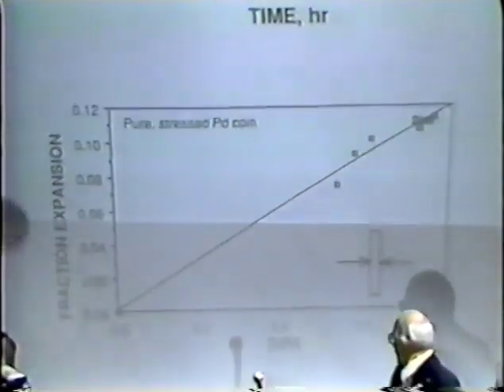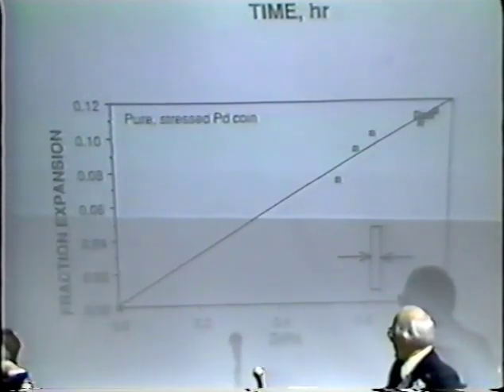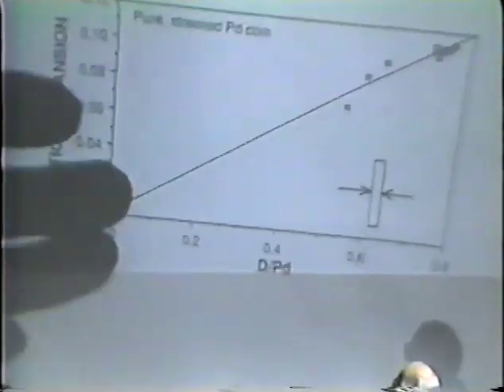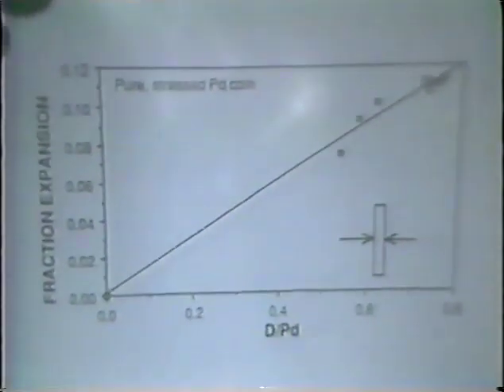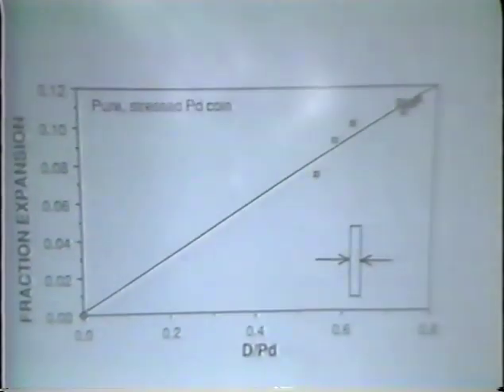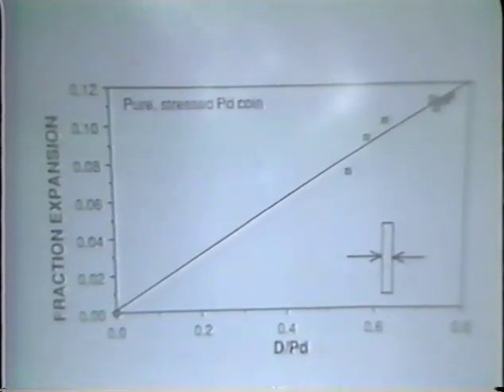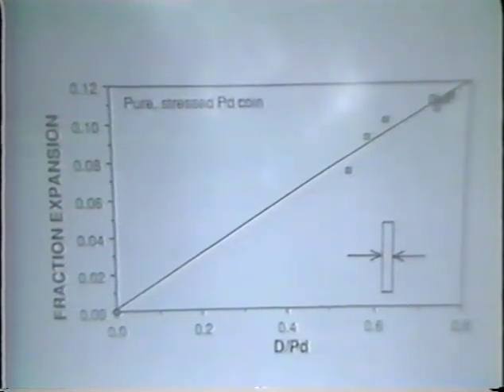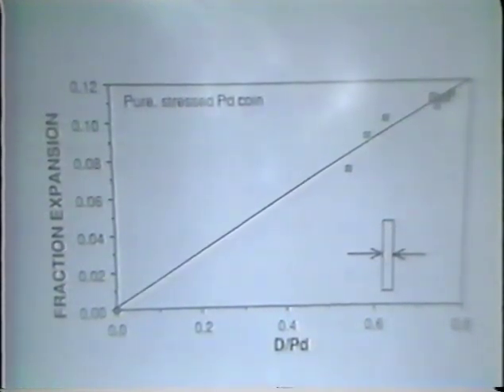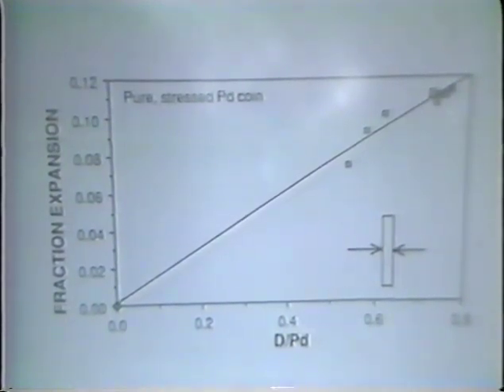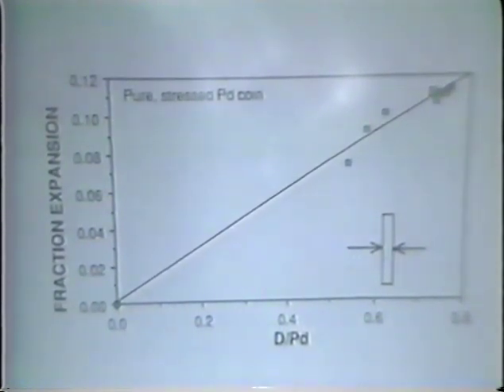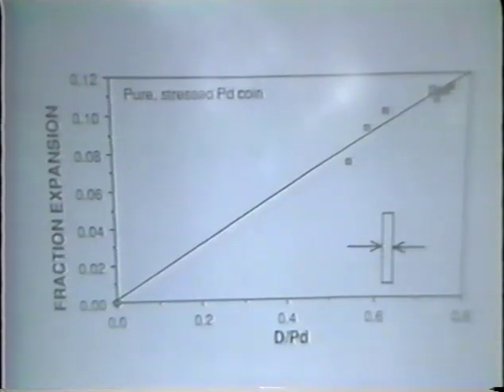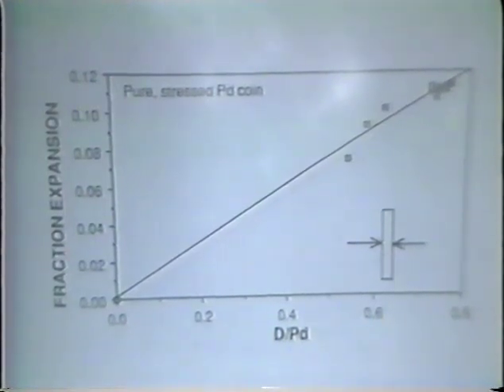Now, while we're measuring the weight increase, we are also measuring the thickness. And I'll get this up so you can see it. And you'll notice that there is a fairly decent linear relationship between the dimension increase and the deuterium to palladium content. This is reported in the literature. It's known. In fact, there have been similar studies. This would be useful to quantify if you were intending to measure your particular ratio. It's a very simple measurement to make.